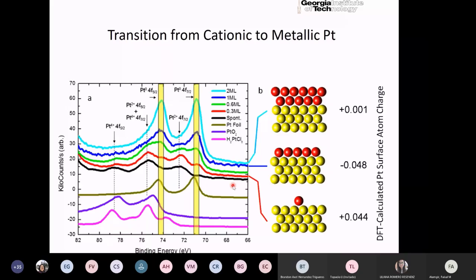All right, so then we essentially tried to do the structure on 3-dimensional graphene. So we had these graphene foams that we generated, and did the deposition on the graphene foam, and we were able to then look at the coverage of platinum and go all the way down to the atomic scale, and you can start to see on high resolution TEM that we again have this 100 like structure, even though this is now very poorly defined graphene. It's not flat graphene anymore. And even in this case, we have this behavior. And what do we see? Well, we see chemically that the potential at which this reaction happens, the ORR reaction happens, depends on the material that is below the graphene.